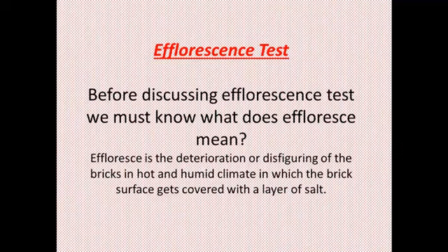The salts are present in the clay, and when the rainwater penetrates into the bricks, the salts get dissolved, and once exposed to the sun, evaporation starts. The salts move along with water by capillary action and form incrustations on the bricks. The salts may be sulfates of calcium, magnesium, sodium, or potassium.